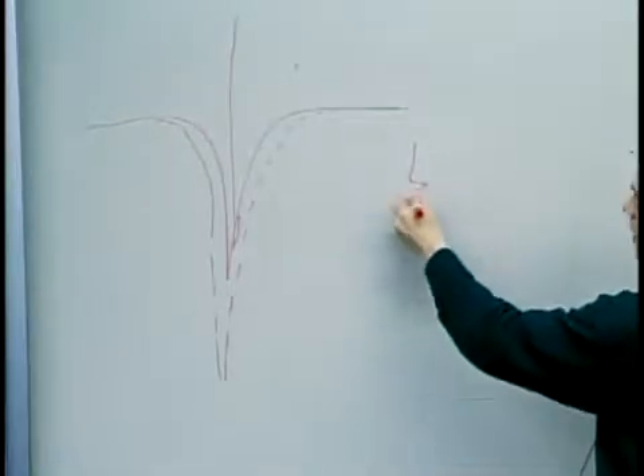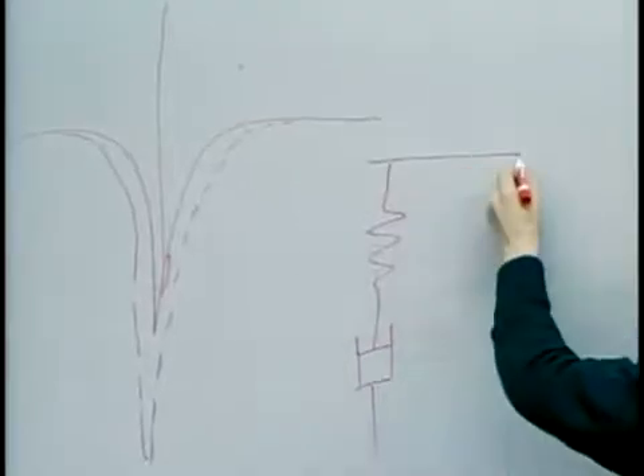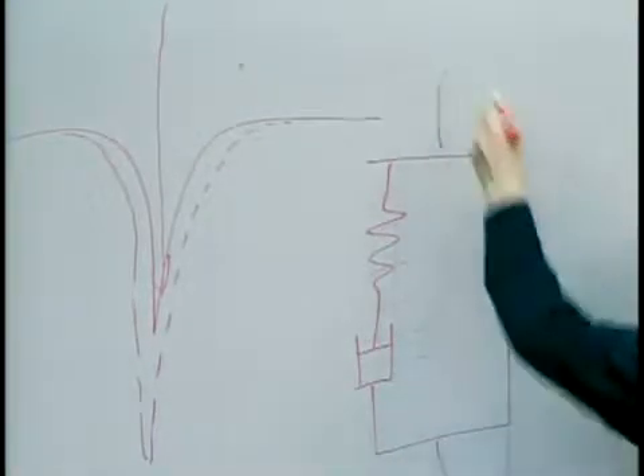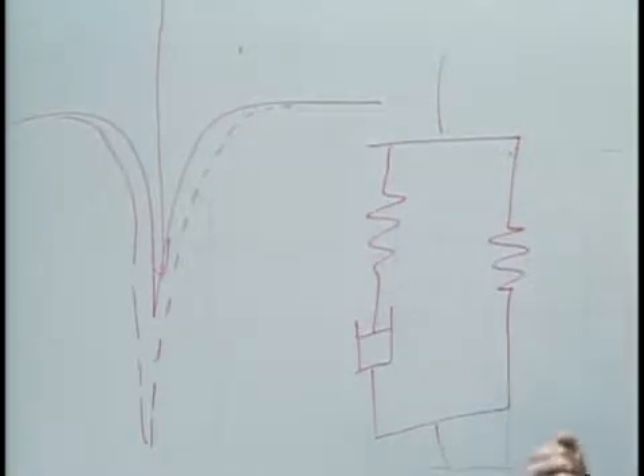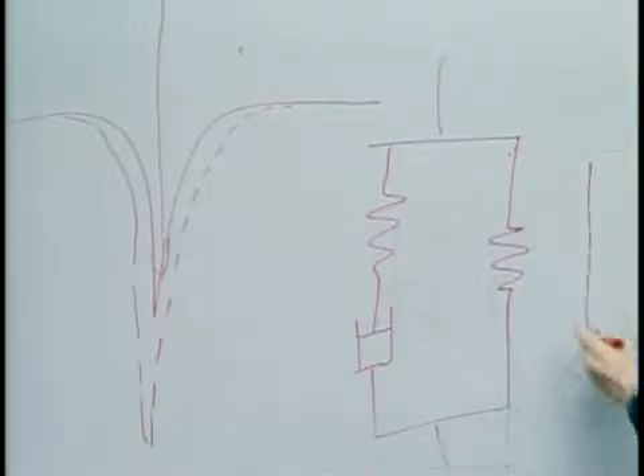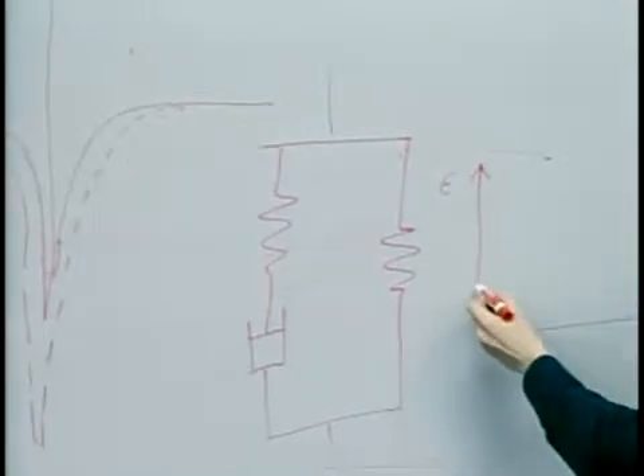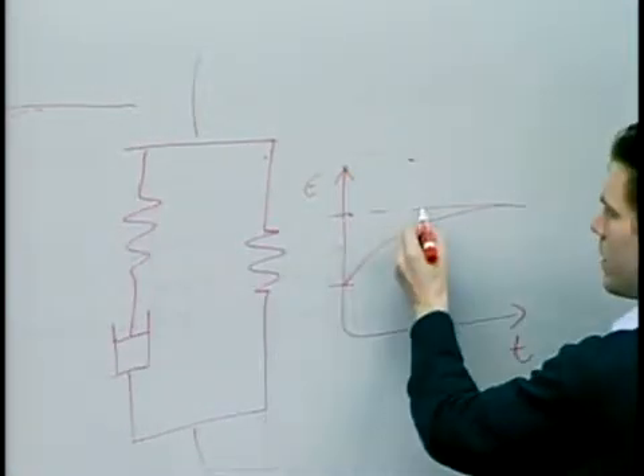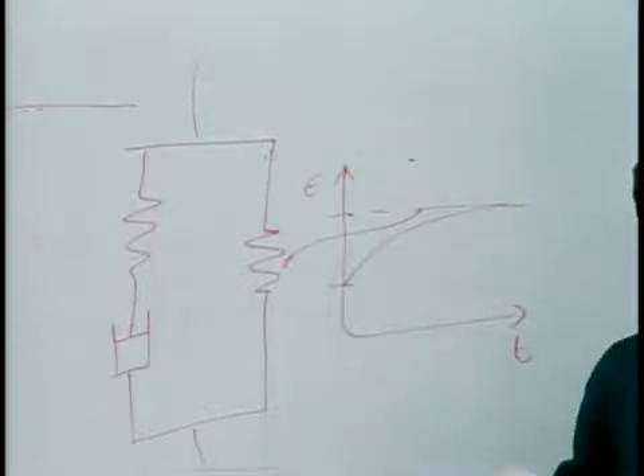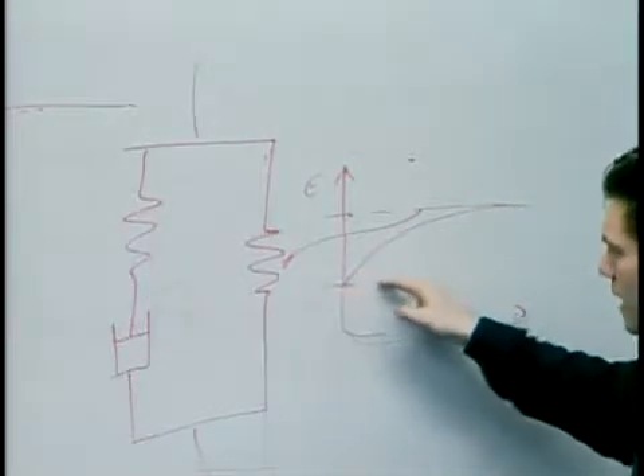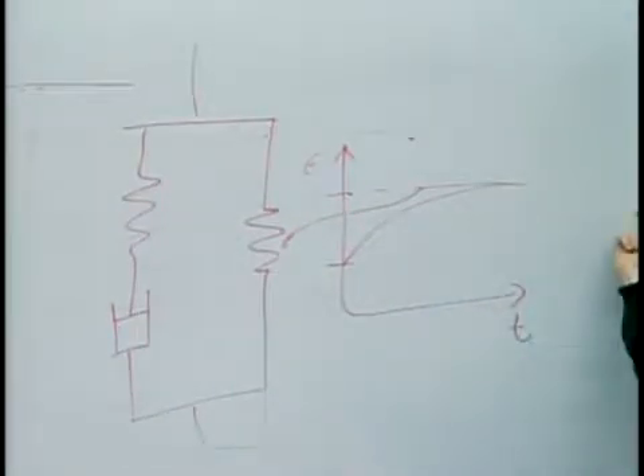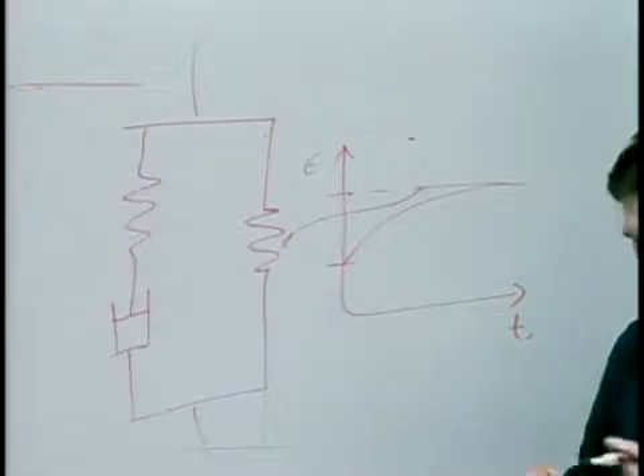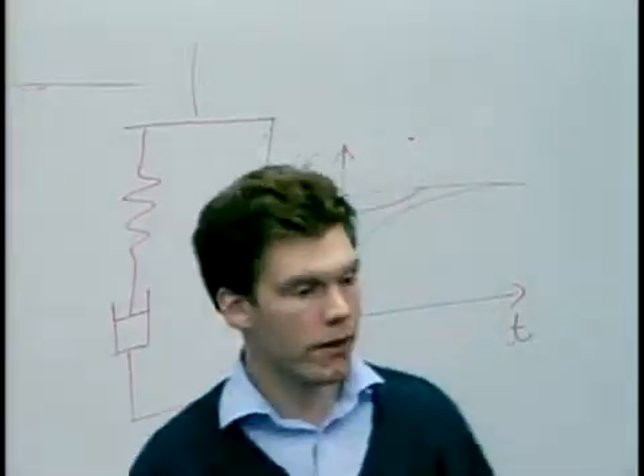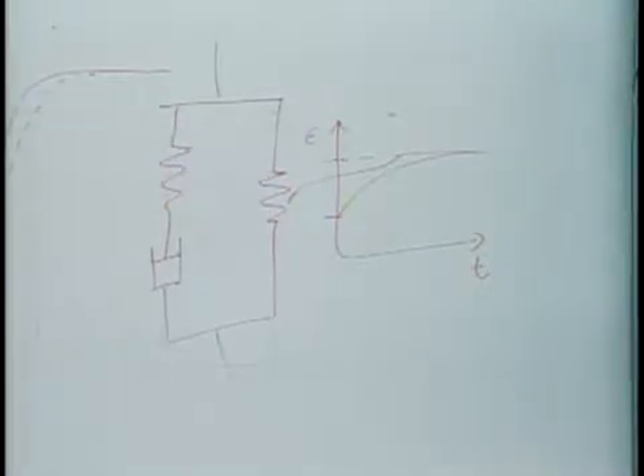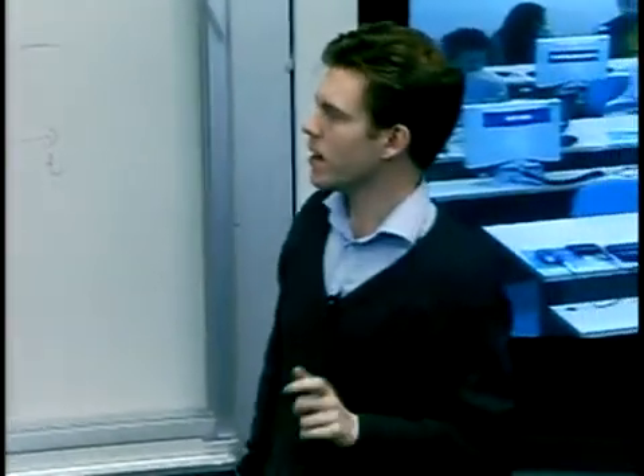You might say, well, what if there's actually a sort of limiting strain where the polymer network is as stretched out as it can be for a particular load, and in that case you would have, I guess, strain against time would asymptotically approach some limiting value that was related to that spring, and that would also be quite easy to compute. You compute a topography at the start of the holding, a topography that would be associated with infinite time, and then maybe interpolate using an exponential function of hold time. But anyway, we just went with a linear scaling, and it seems to work remarkably well for these particular conditions, 110 degrees C, which is a few degrees above glass transition.